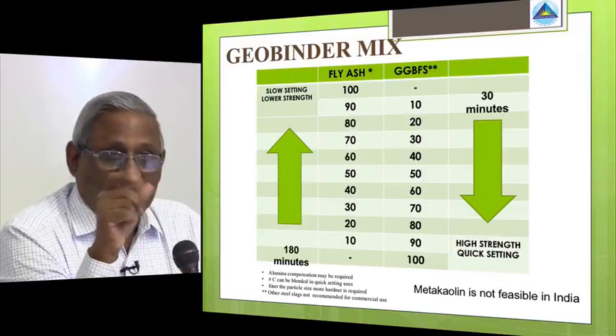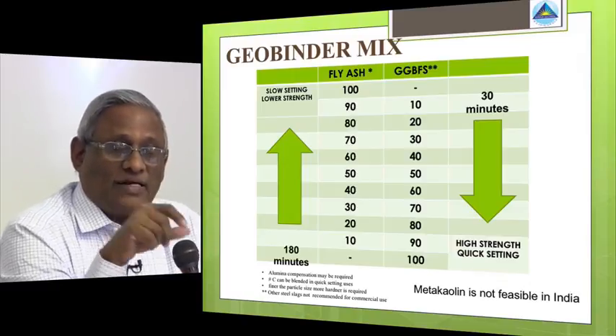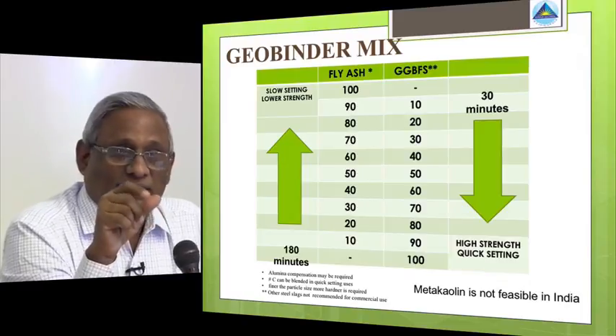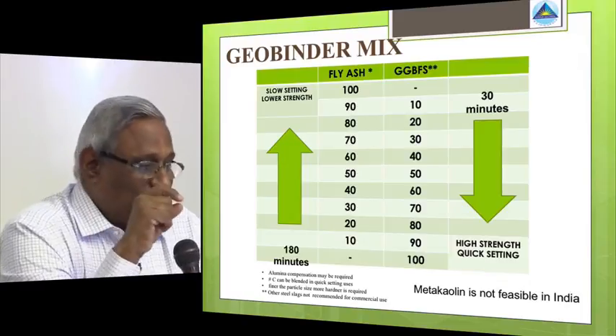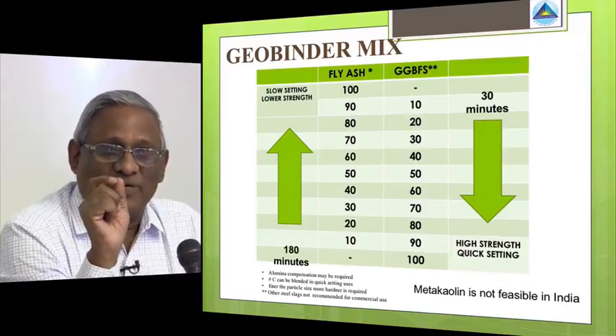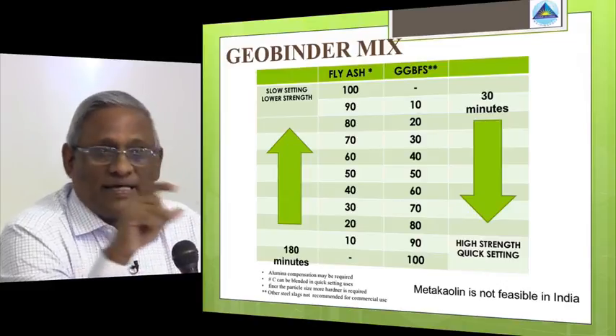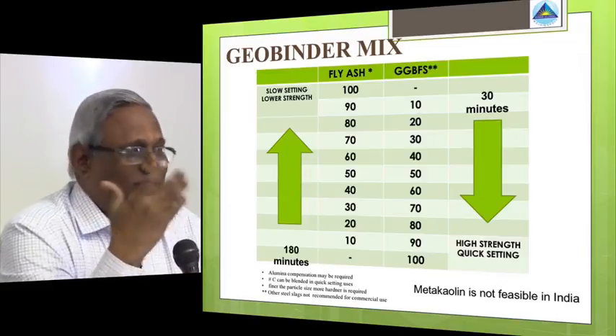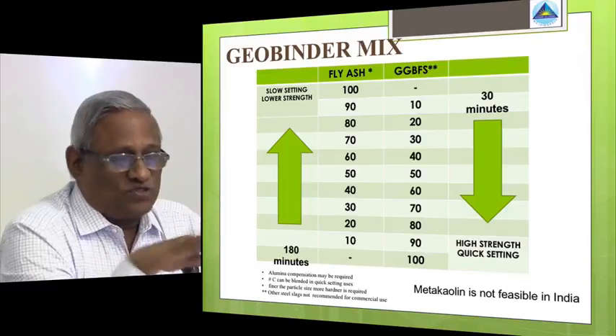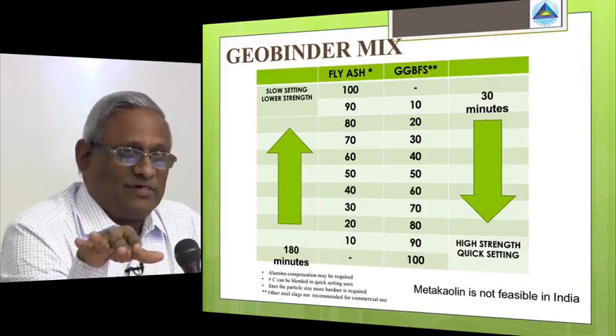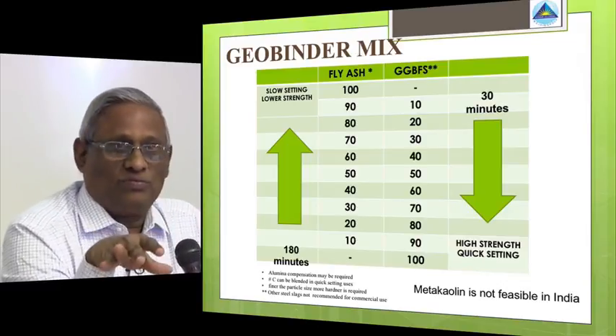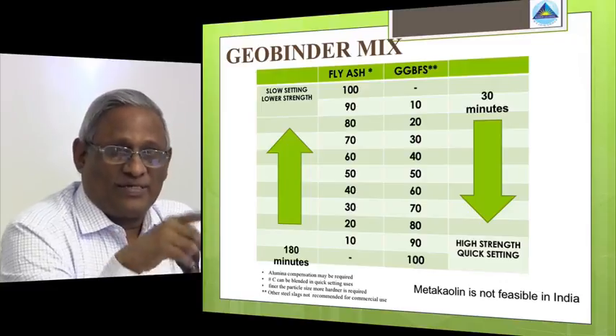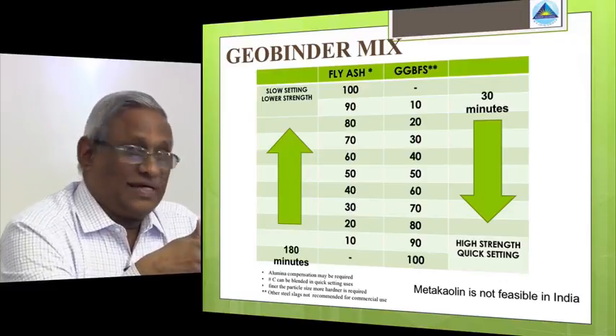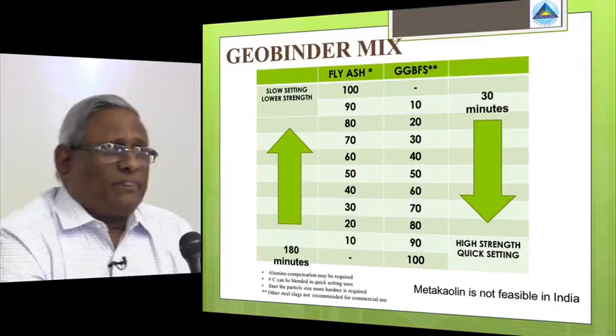Sometimes the sum of the alumina content in your fly ash and GGBS, if it is less, we separately add alumina to compensate. Otherwise, it doesn't get set properly. Some of the fly ash samples. So once you standardize on a fly ash, there is no problem. But if the alumina content is low, then you need to compensate with external aluminum oxide.